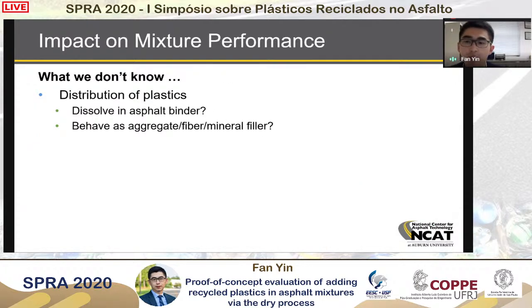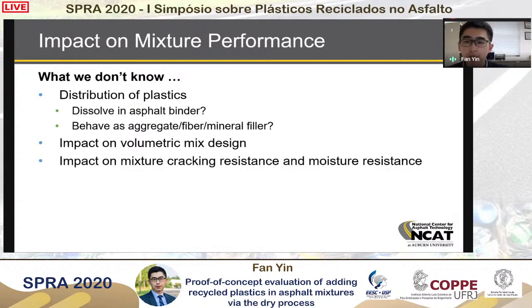But what's missing from the literature is the distribution of the plastic. I mentioned this before. When we add the plastic into the mix, do they dissolve in the asphalt binder, or do they stay outside the binder phase as solid particles in the form of either aggregates, fiber, or mineral filler? I don't think there's a good understanding there. Also, we don't know the impact on the volumetric mix design. Because of the very different specific gravity between the plastic and aggregate, it will affect those volumetric properties. And in the next few slides, I'm going to show some data that prove that discussion. I think the most important part that is missing at this point is the cracking evaluation and moisture damage.